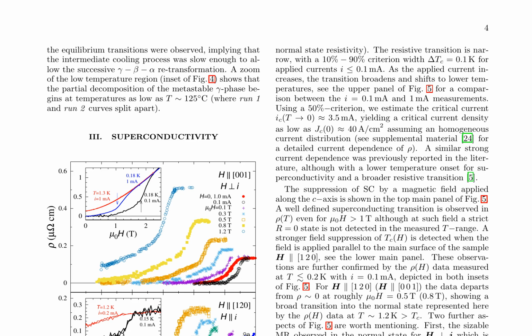The research on the superconductivity in the gamma PtBi2 compound discusses the experimental results, focusing on the equilibrium transitions observed in dilatometry measurements. These indicate a slow cooling process allowing for the successive γ-β-α retransformation. Resistivity measurements at very low temperatures reveal a superconducting transition with a critical temperature Tc equals 1.1 K, defined by the 50% criterion.